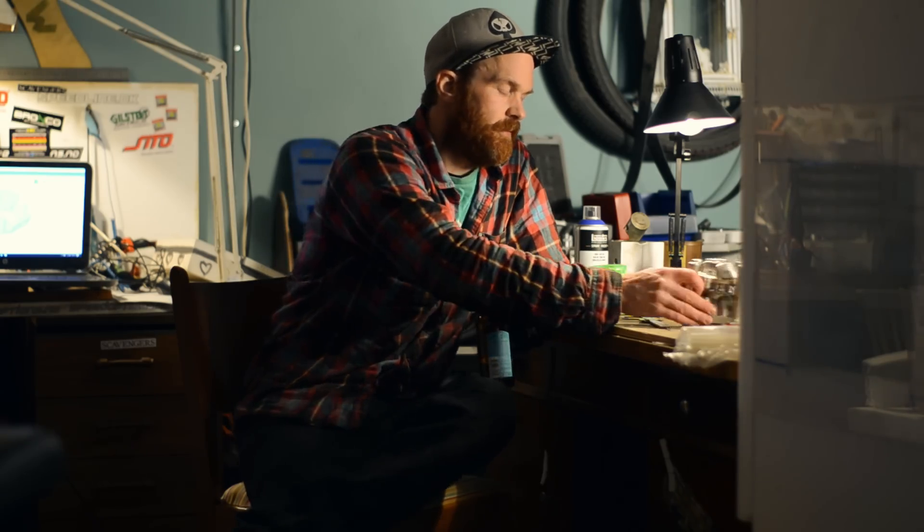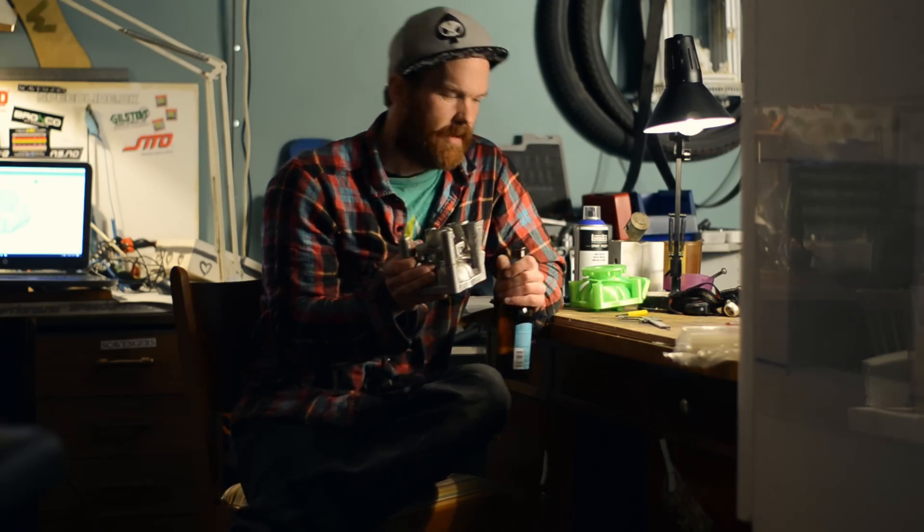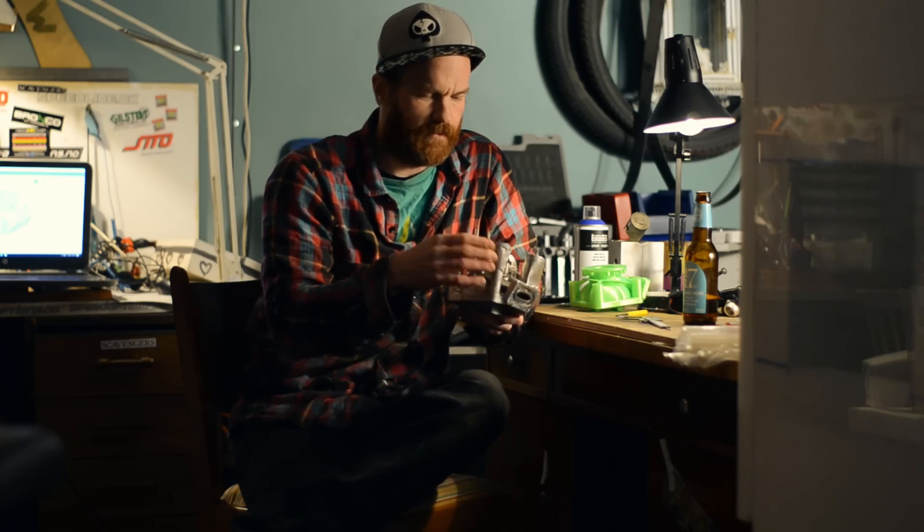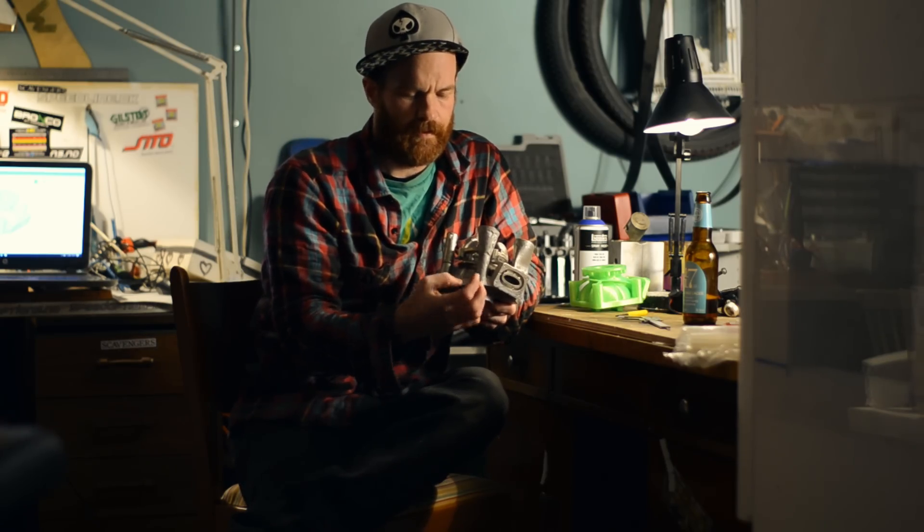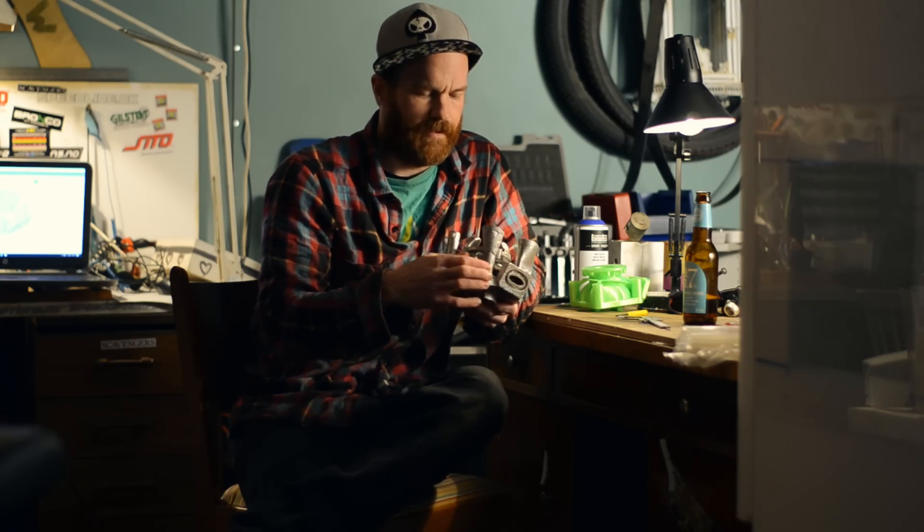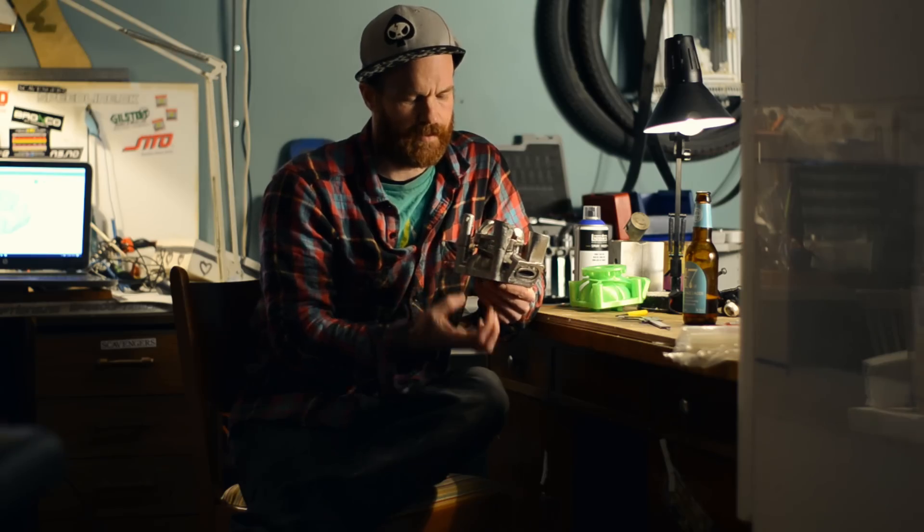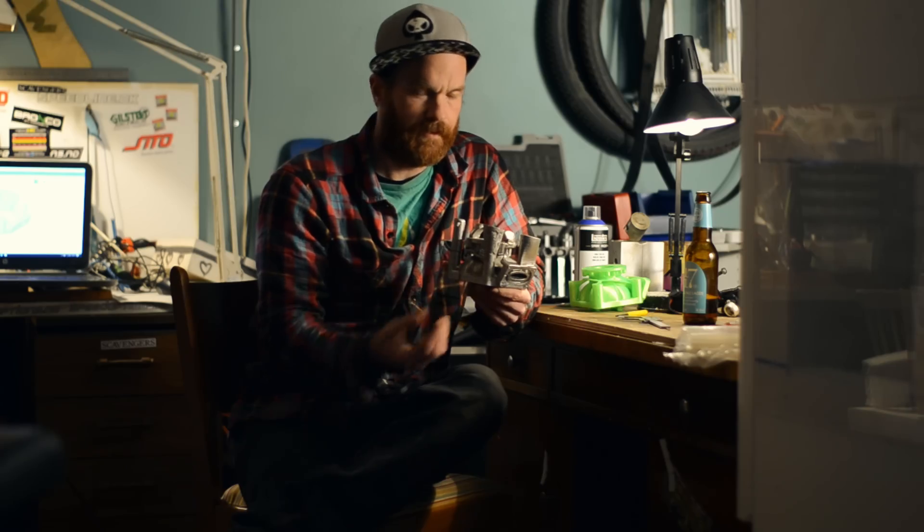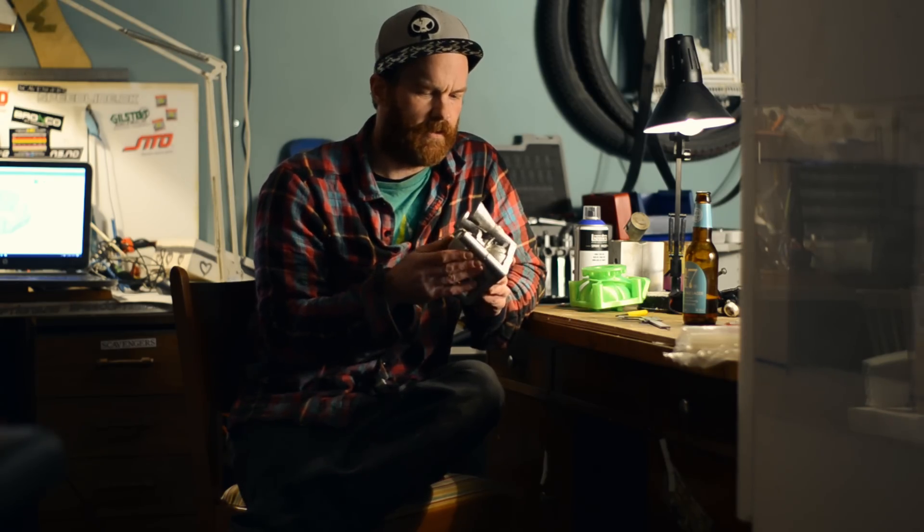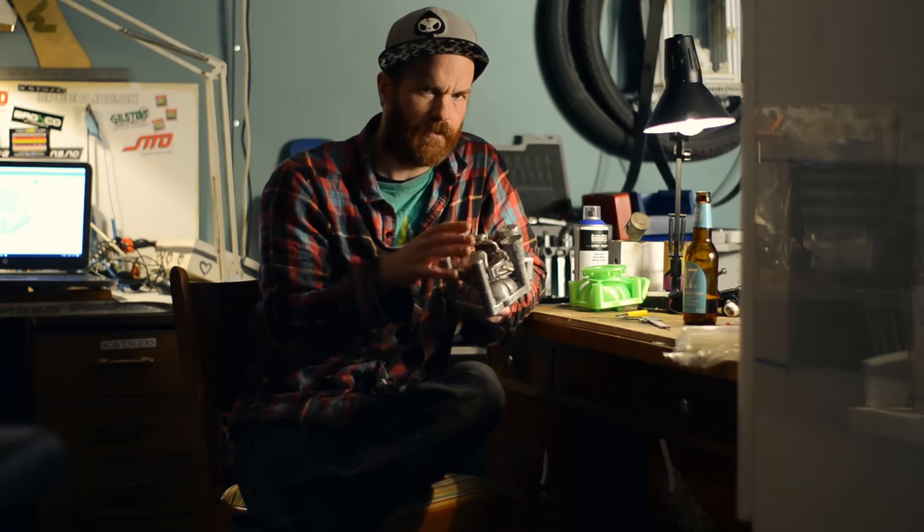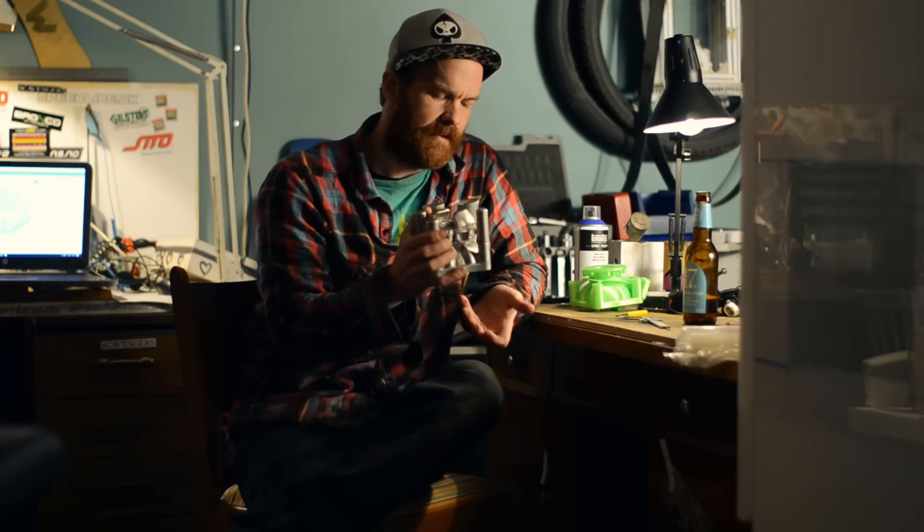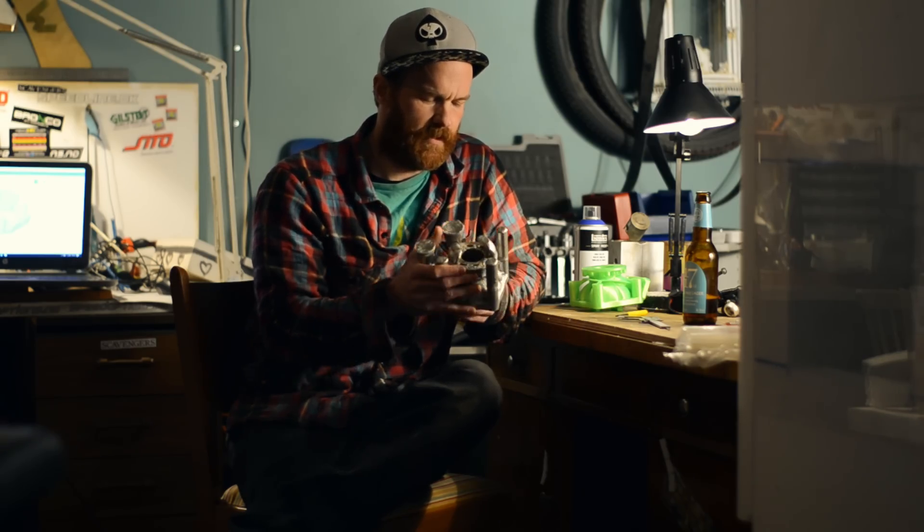Also, I'm going to make the—I'm not going to have the main sprue part of the casting, but rather have it end in a well, a bigger portion down here, and then gate it into the casting. This to contain the first slug of impurities in that well and then start feeding the casting. I was originally going to do that here too for this one, but I realized I did not have enough metal. Had I made that well, I probably would have come out even worse than what I did with this one.